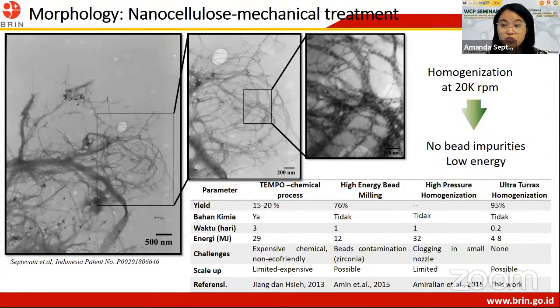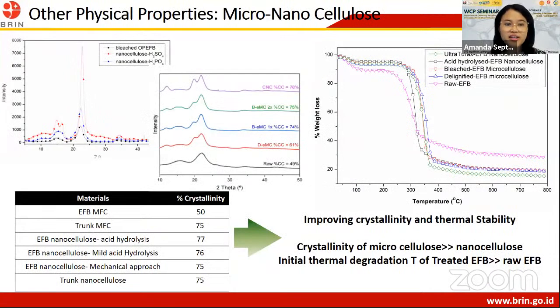experiments using the mechanical approach, that our approach can produce nanocellulose without impurity and with lower energy, which is very promising for the development of nanocellulose at a large scale. So for the other physical properties such as the crystallinity and the thermal stability by TGA, we can see that after the process of producing nanocellulose, we can get a crystallinity above 70.